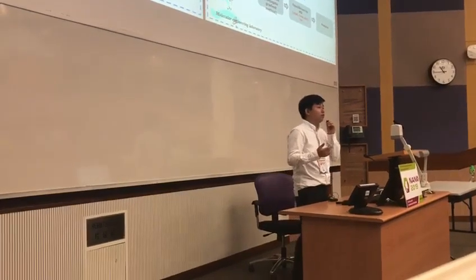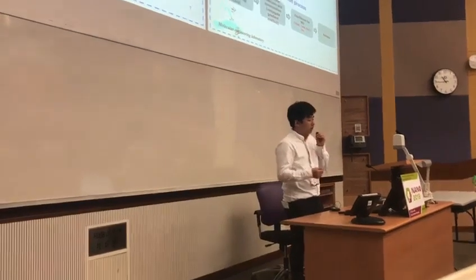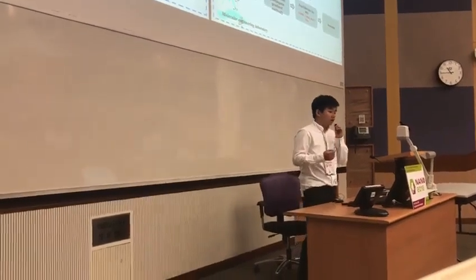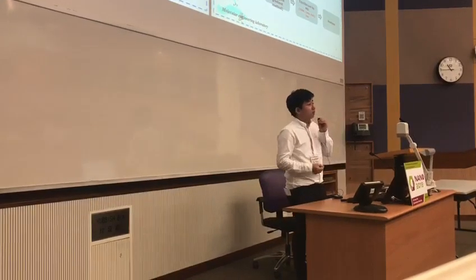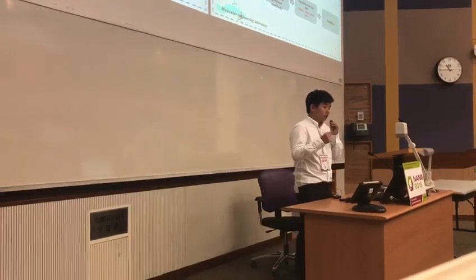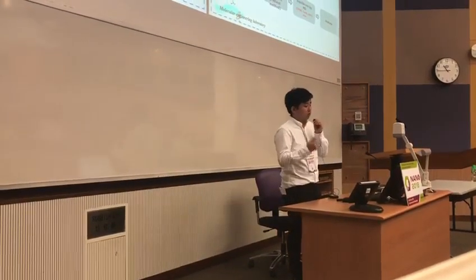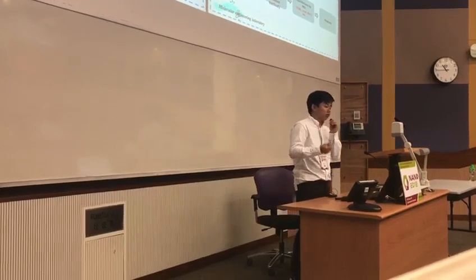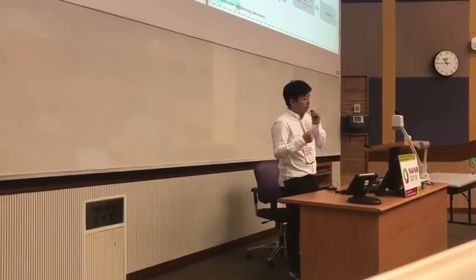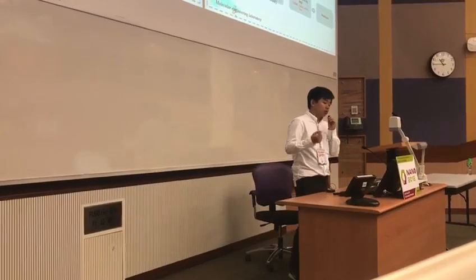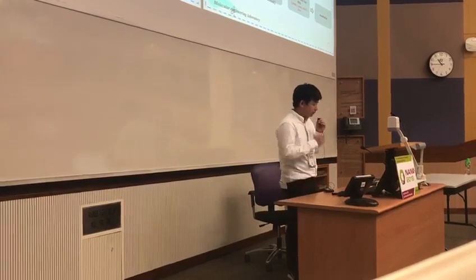The principle of basin hopping is changing the distance and the orientation between the peptide and the Pt facet randomly. Next, the random structure is minimized by molecular statics calculation and approaches a local minimum structure. Finally, after obtaining a set of local minimum structures, the most stable adsorption structure may be approached.